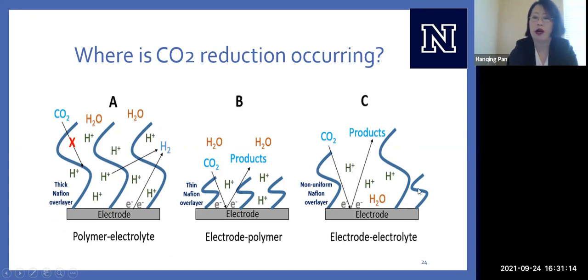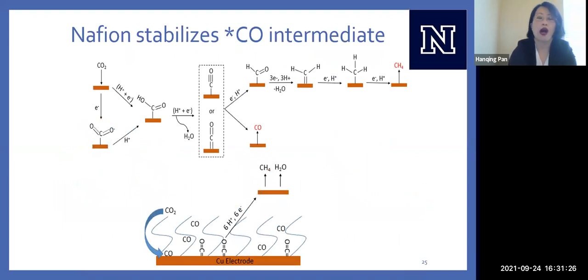But we know from our electron microscope experiments that this is not the case because our Nafion overlayer is very uniform. So there are no holes in our Nafion overlayer. So why is this happening? Why are we able to make such high yields of methane? The hypothesis that we have is that the Nafion somehow is stabilizing the CO intermediate.